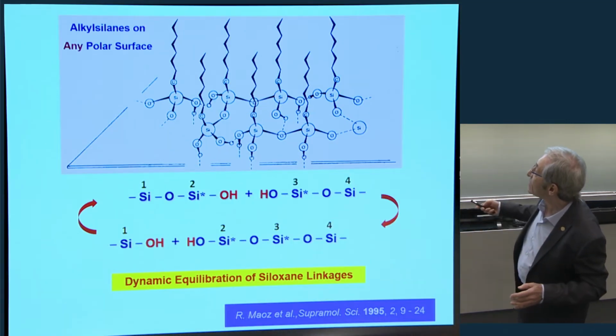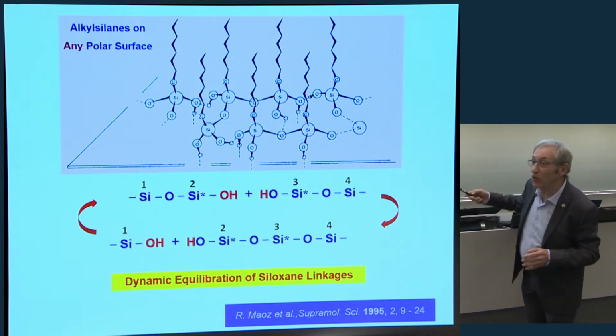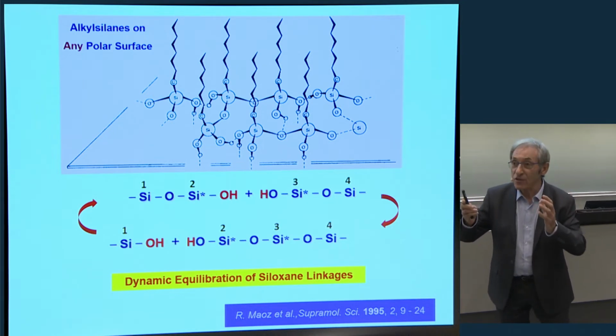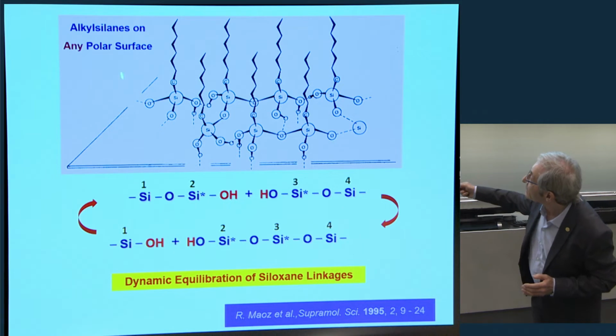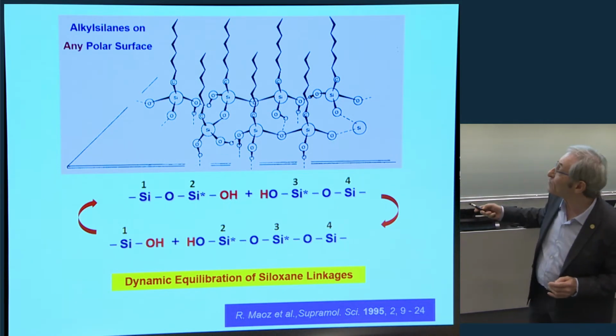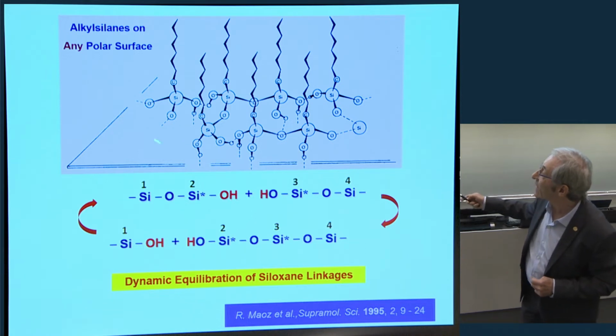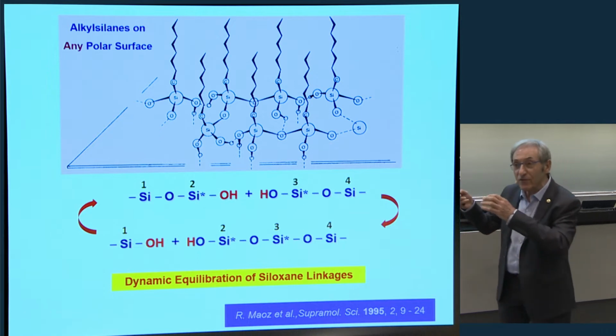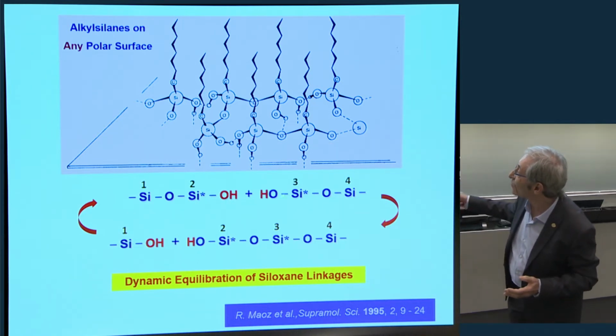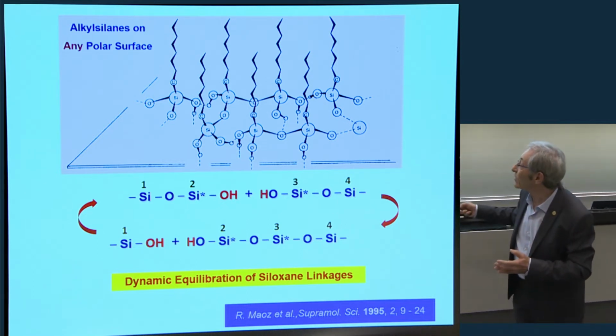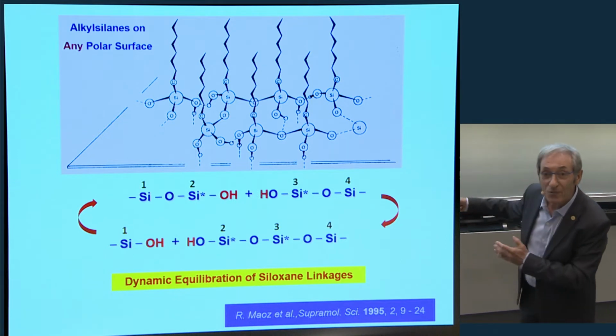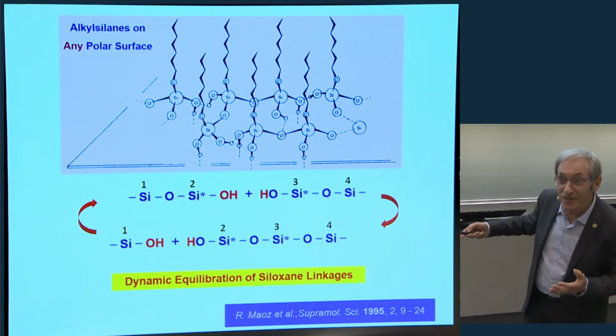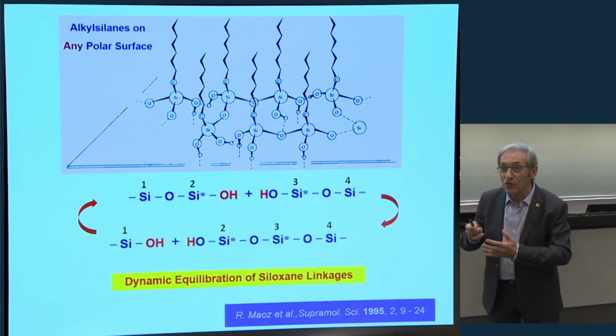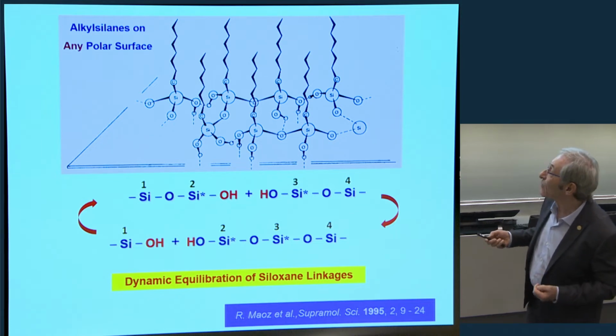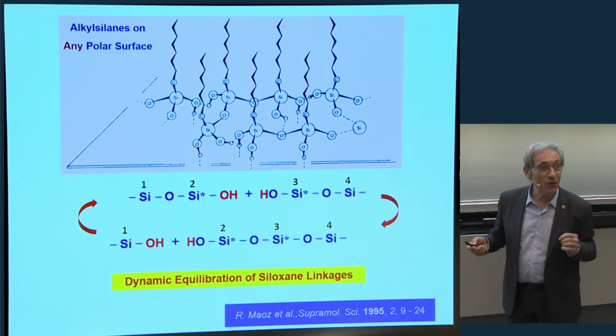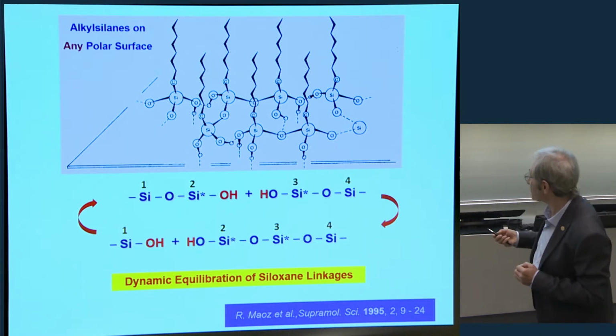You can see this is a model where these are the hydrocarbon tails that are packed together by van der Waals forces, and the hydrolyzed silane head groups can bind laterally, and there is a lot of dynamic equilibration. It means bonds can form and bonds can break. This is like a water molecule moving around. When a water molecule is taken away, a bond is formed. When a water molecule is incorporated, this is hydrolysis, and the bonds are broken. So this gives a lot of mobility, which is necessary for creating a self-healing process in which you get the perfect structure. This is very important.